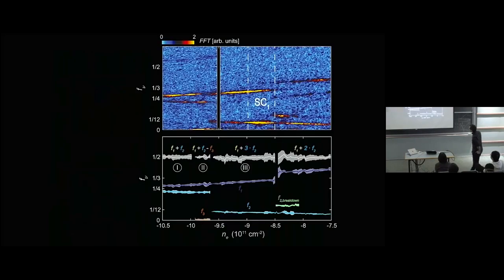So TC is much higher, and we're going to go ahead and play our trick of really trying to understand the normal state Fermi surfaces. And we see that for this first superconductor, which is quite low TC, it's emerging from a normal state that doesn't break any symmetries, except for the fact that the spin-orbit coupling itself is breaking the spinless time reversal symmetry that is normally there in graphene.